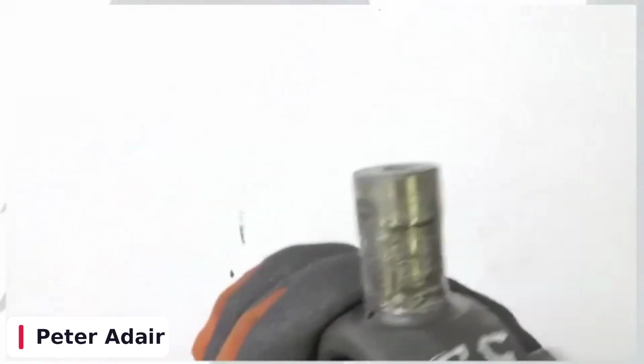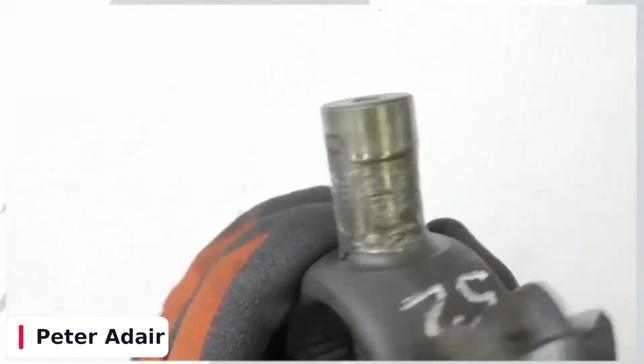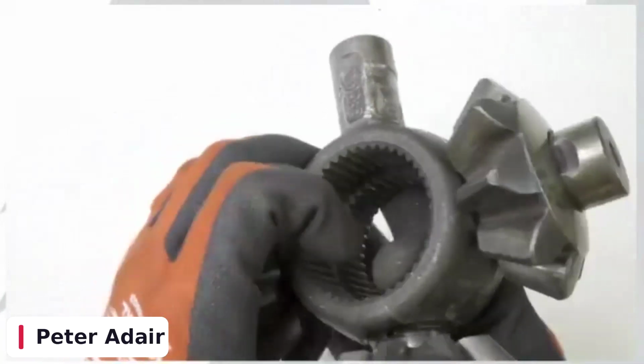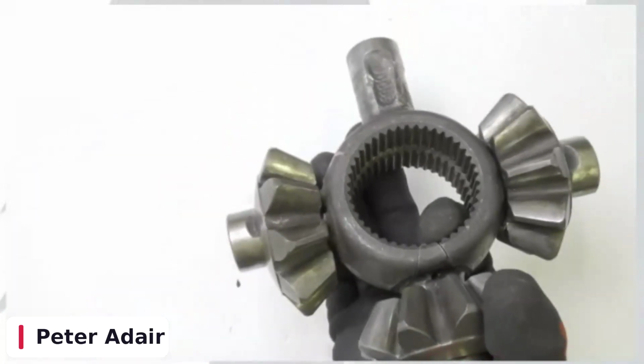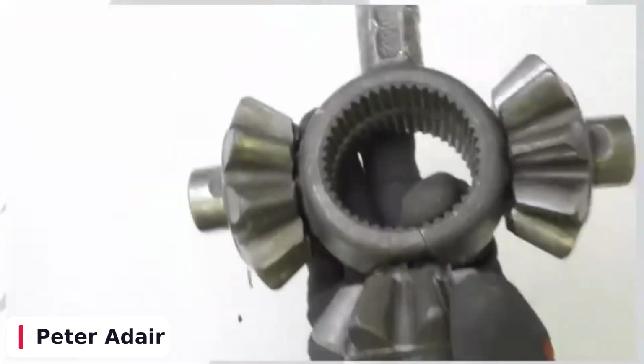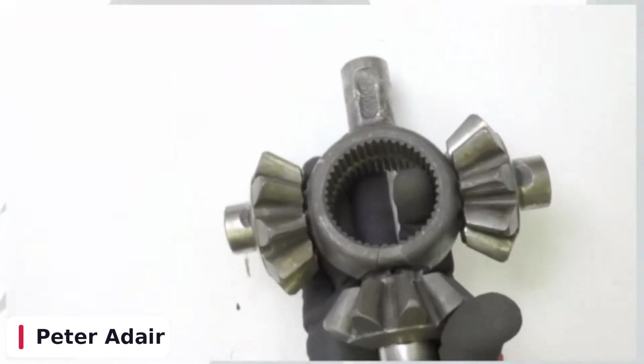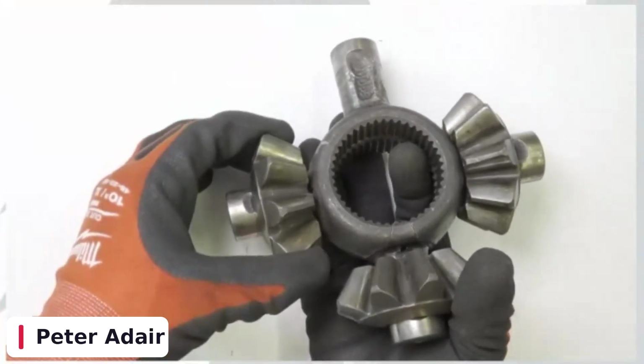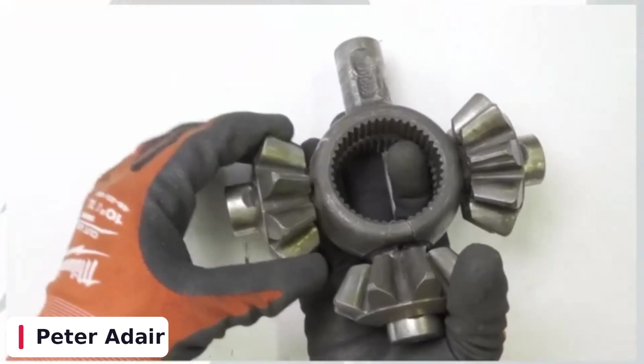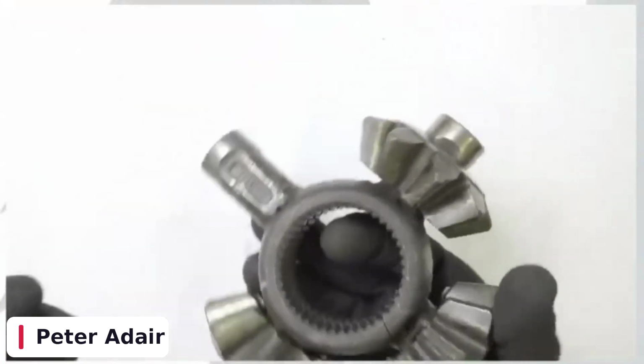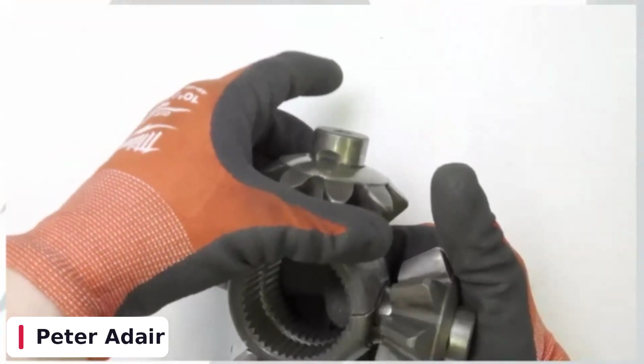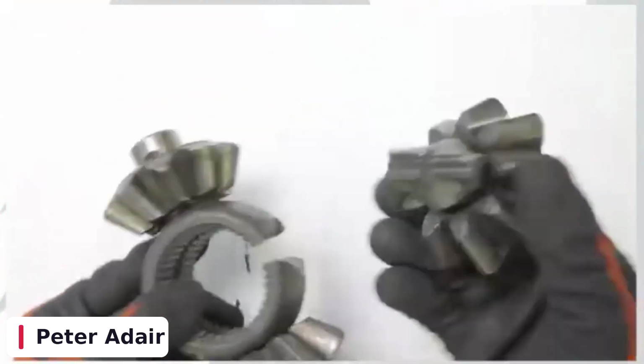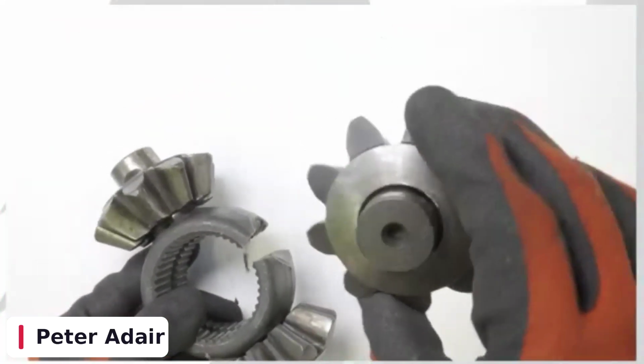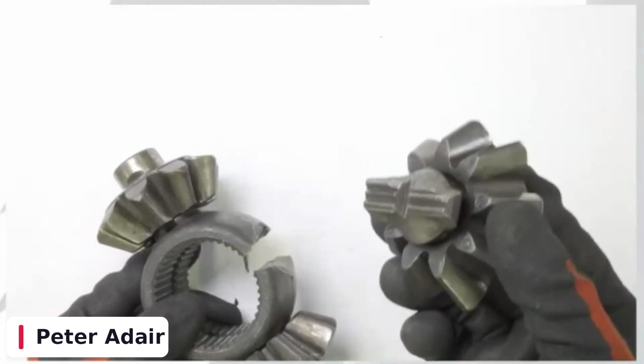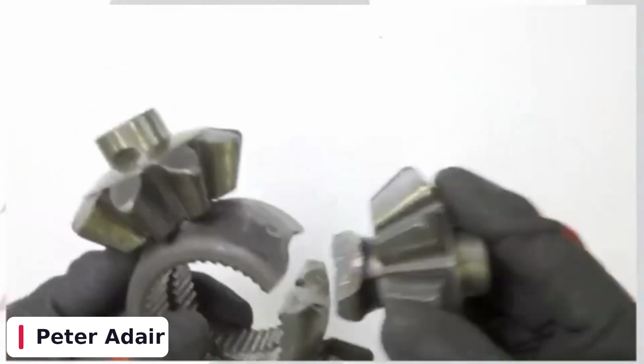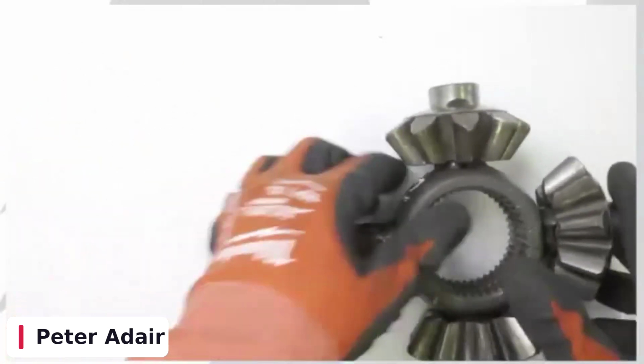So you can see the metal to metal, the friction welding or the galling, right? These guys are still attached. They still spin. But the key thing with any spin out or excessive differentiation is, do they come off? And the answer is no. On a normal built carrier, these pinions would come off of the cross. And as you can see, this one is fully seized and will not spin, which is why we broke at the cross hub.